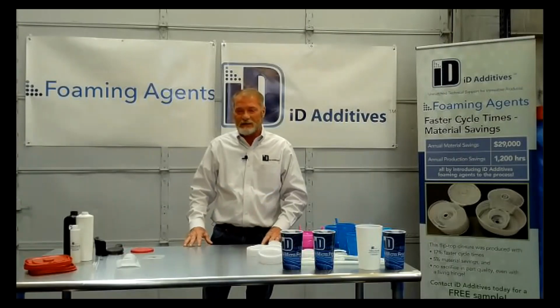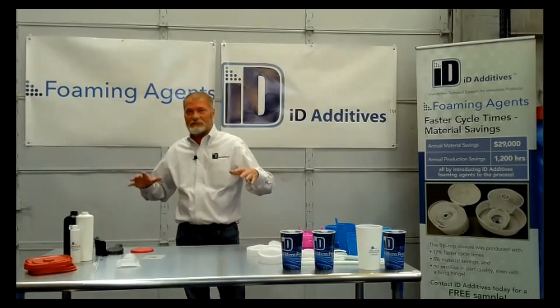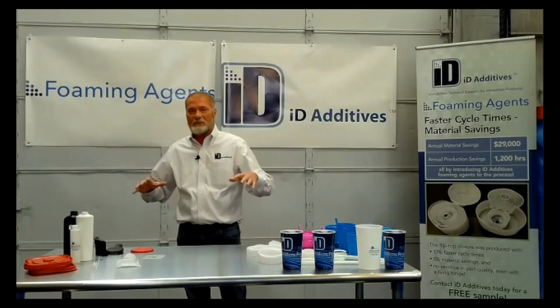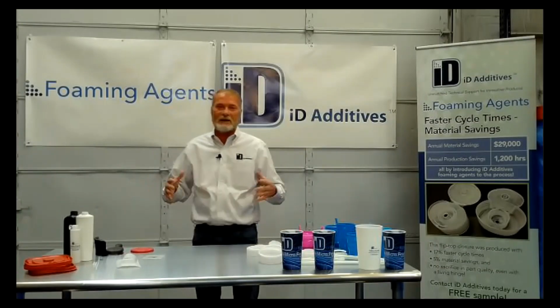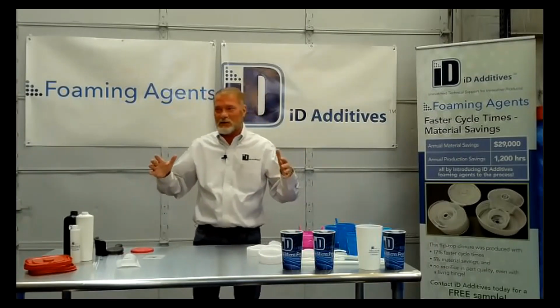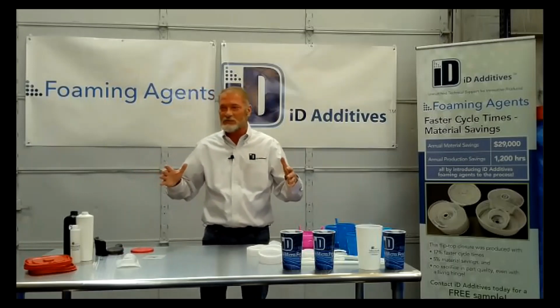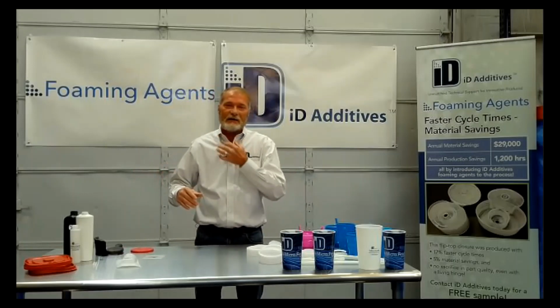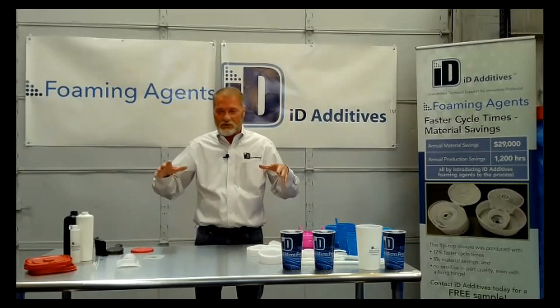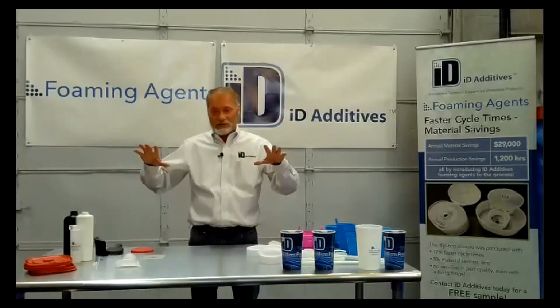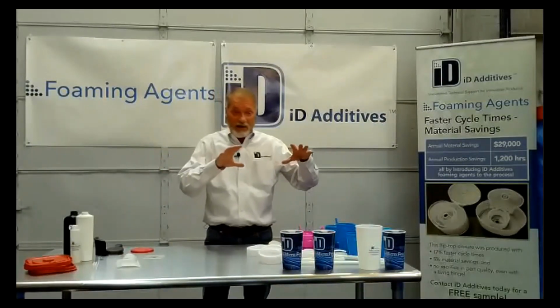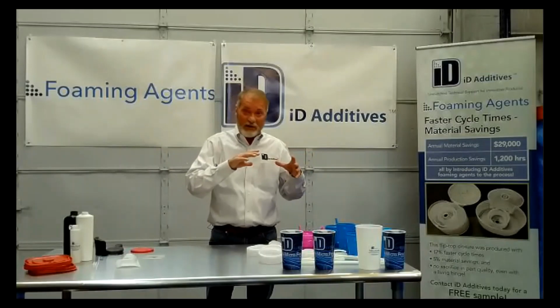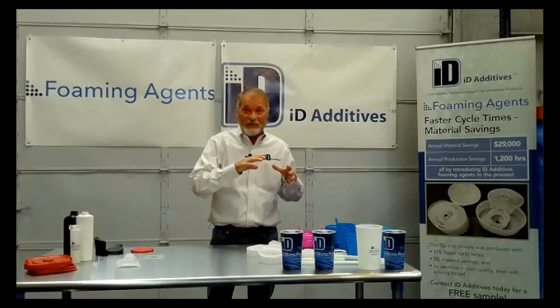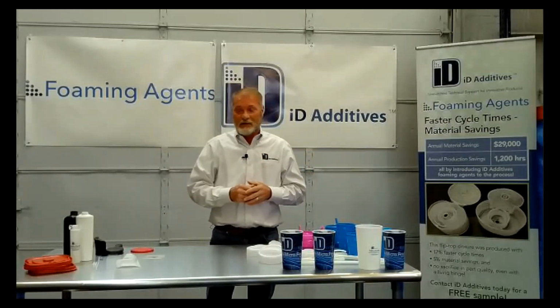What that does is keep the foaming agent in solution, because under pressure, the foam can't expand. So you want to keep as much pressure on that screw as possible, and control temperatures, so that you control that bubble, and when it hits the die, that's when you want it to expand.